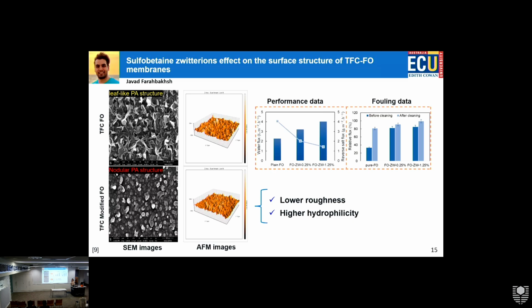We don't want it. It happens when we have a defective membrane, or when the membrane properties in terms of hydrophilicity and hydrophobicity are not advantageous. So the reverse salt flux decreased and the flux increased, which shows that zwitterionic materials have significantly improved the efficiency of the membrane.